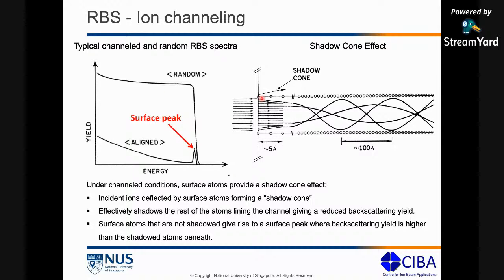But what happens here at the edge? You have these two atoms at the surface. These two atoms at the surface will deflect the incident ions that hit them. So some of these incident ions, the ones that are here and the ones that are here, will collide and deflect from these surface atoms, and that gives rise to what we call the shadow cone effect. What that means is that these surface atoms are essentially shadowing all of the atoms that lie below them. So when these incident ions collide with these surface atoms, you get a shadow cone effect, and the ones that collide from here will backscatter. So these are the only two backscattering events that will occur when you have channeling.